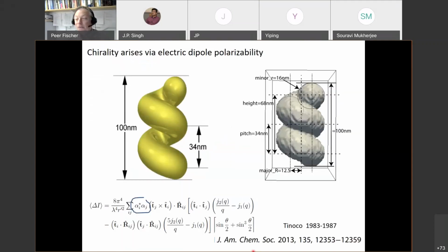And the beauty now is that we can make them small enough to minimize scattering effects, but large enough to be much, much bigger than a molecule. And moreover, we can make them from, for instance, plasmonic metals, so that we have a large conductor, basically a very strong antenna that can interact with light. And in this case, it's a spatial, a shape chirality, because we are having this helical shape. And this then means it has an enormous polarizability, and in particular, it also gives rise to optical activity, i.e. it will interact with left and right circularly polarized light.